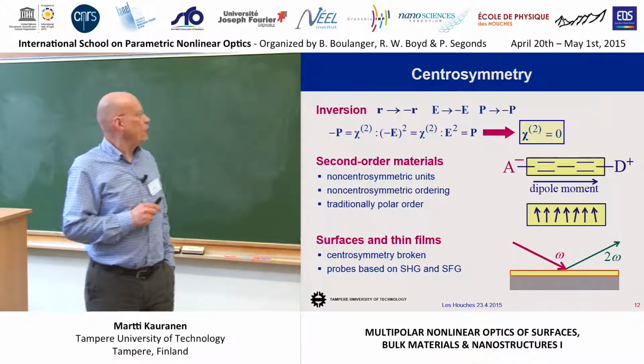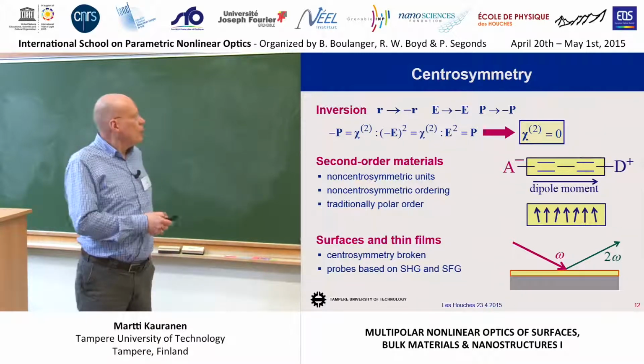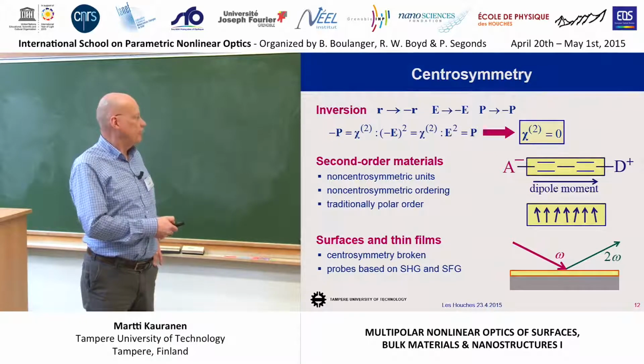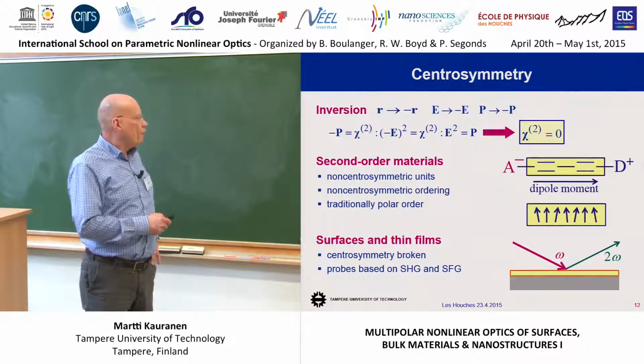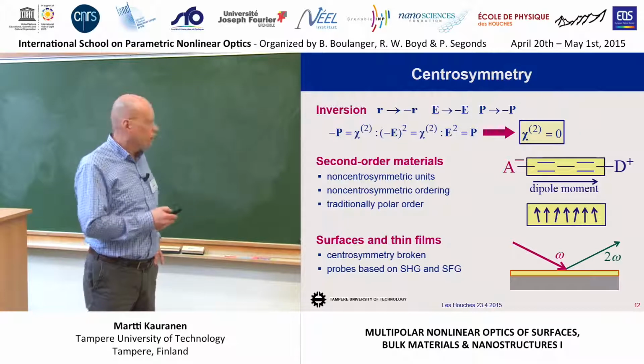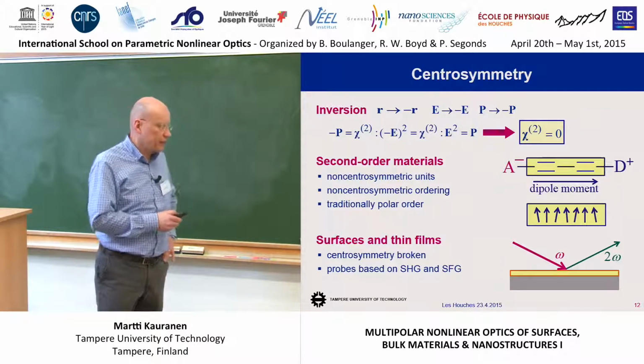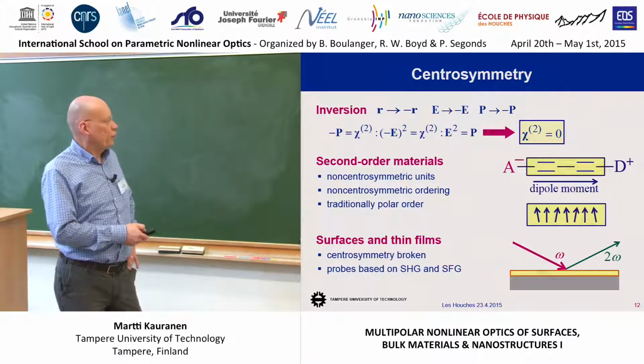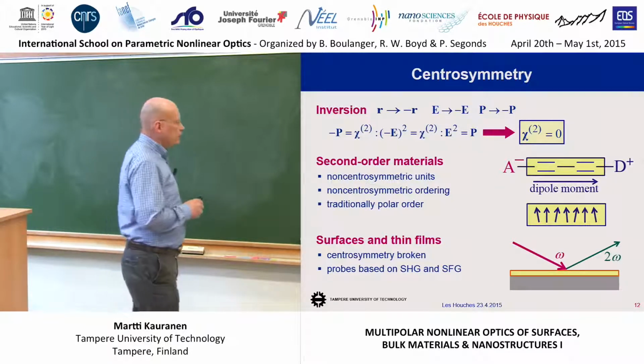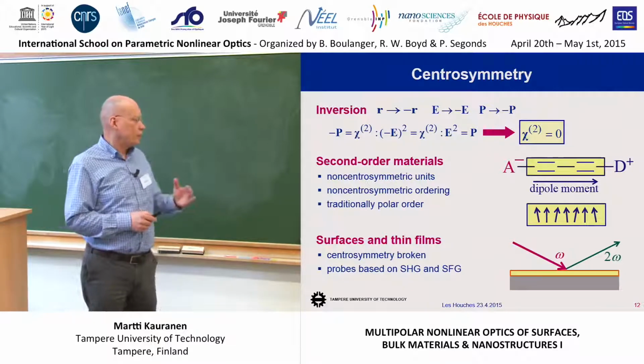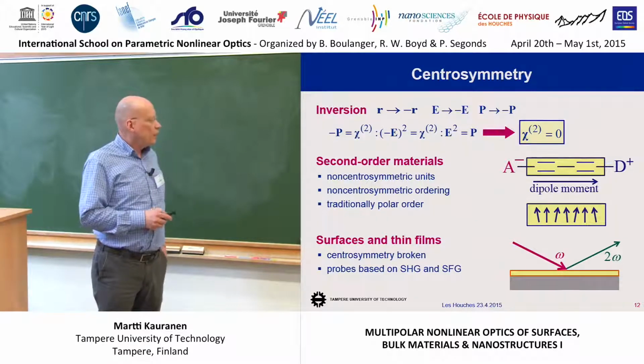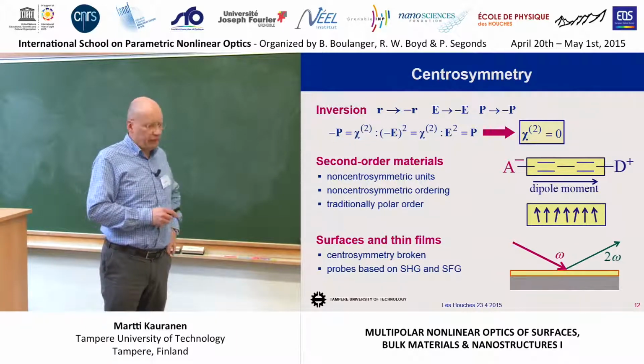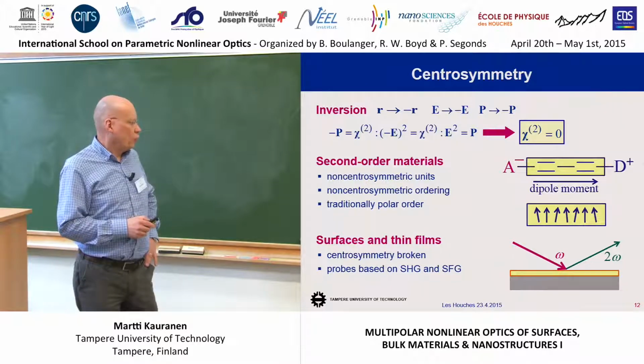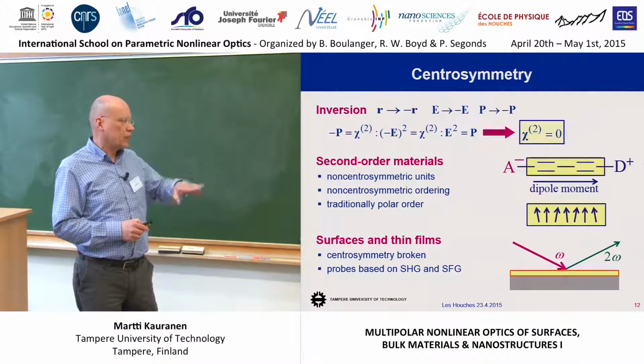Therefore, people who are developing second-order materials are looking for, first, non-centrosymmetric units. This is a molecule which has broken symmetry in this direction. There's a molecular dipole moment. And furthermore, you have to order these units to break the centrosymmetry in the macroscopic sample. And again, in molecular nonlinear optics, you will pole the sample so that the molecules roughly point, let's say, upward. Another interesting thing is that your symmetry is always broken at the interface between two materials. And therefore, second-order effects, second-harmonic generation, and even more so sum-frequency generation, are very nice probes to study surface effects, let's say the ordering of molecules on a substrate and things like that.